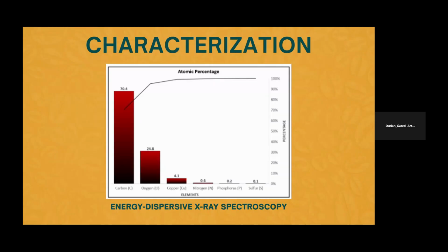The high carbon content, combined with the significant presence of oxygen, supports the synthesis of GOQDs. So GOQDs are known for rich oxygen functional groups, such as hydroxyl, carboxyl, and epoxy groups, which improve their solubility, stability, and reactivity, as confirmed in this EDX analysis.